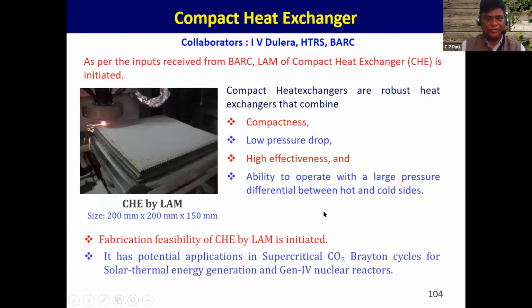Another beautiful example is making the compact heat exchangers, where you have compactness, low pressure drop, high effectiveness, everything built in. And we are able to make small orifices and small channels throughout the heat exchanger, and the size is 2 millimeter by 1.5 millimeter rectangular shaped. This is possible here, which is not possible to have conventionally.